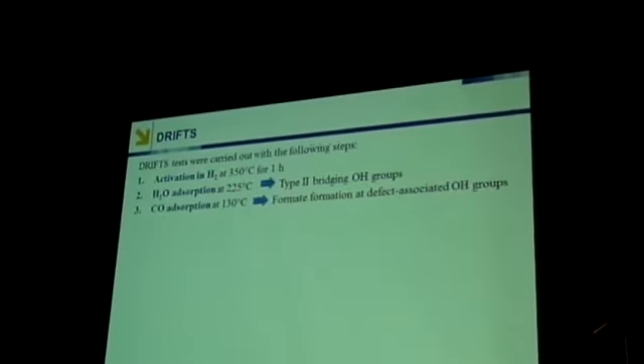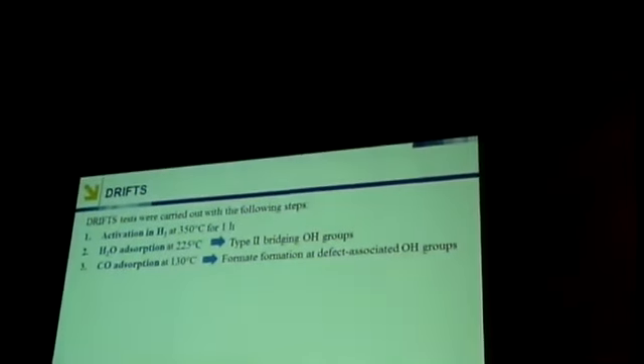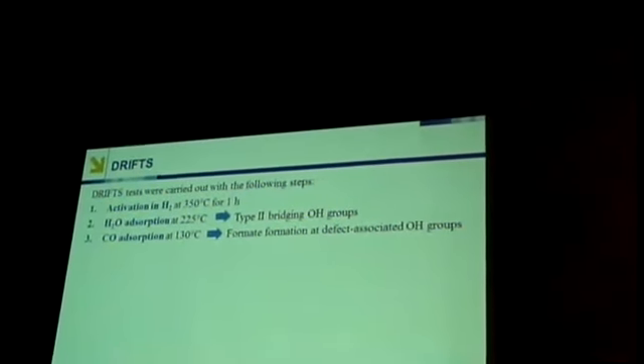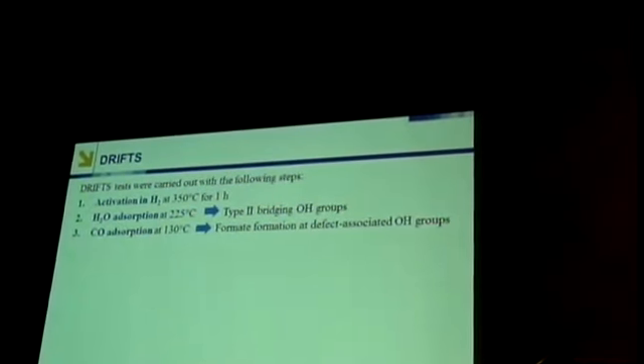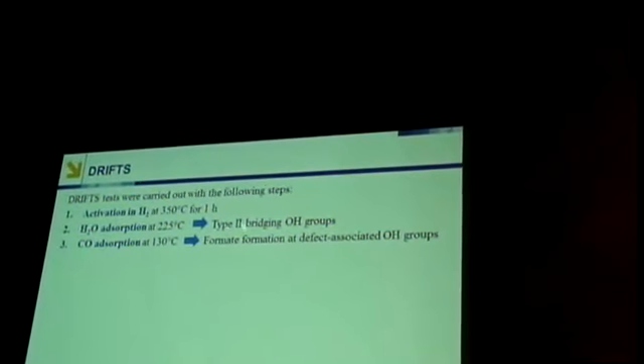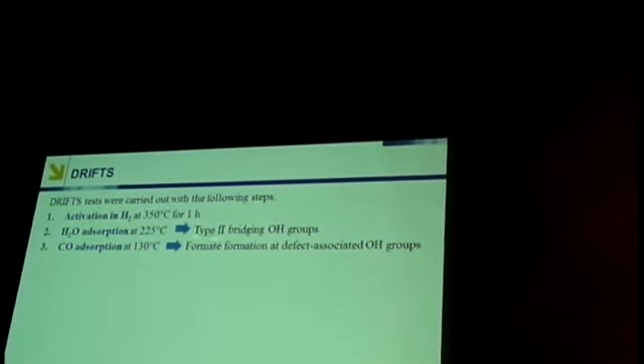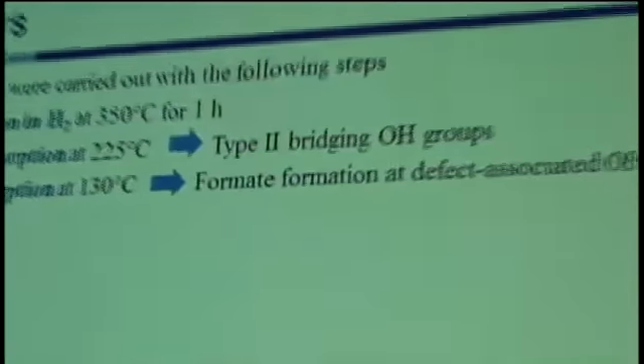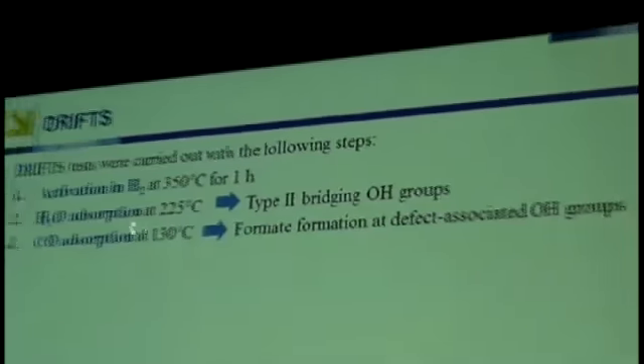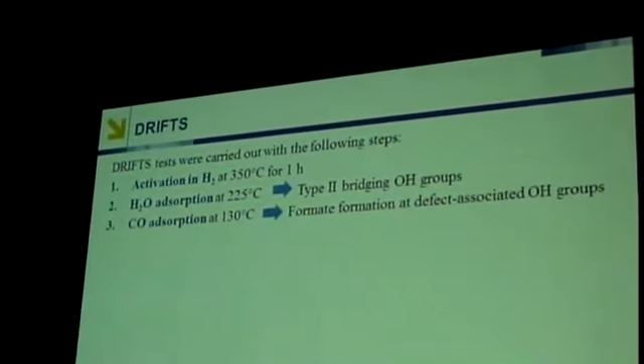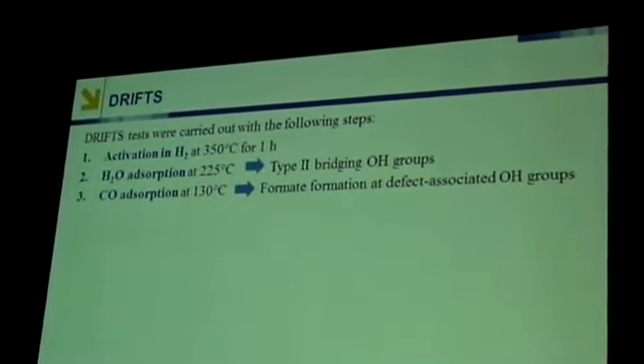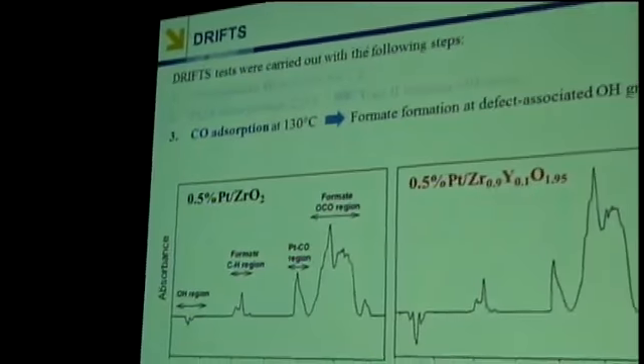So we wanted to look a little bit more at what was going on with the 10% yttria-doped catalyst. So we removed the carbonates and steamed the catalyst to form the defect-associated OH groups, and we carried out CO adsorption to form formates at those sites. Now, as I said, without the presence of water, the formates are quite stable. So we can look at those in the absence of steaming.